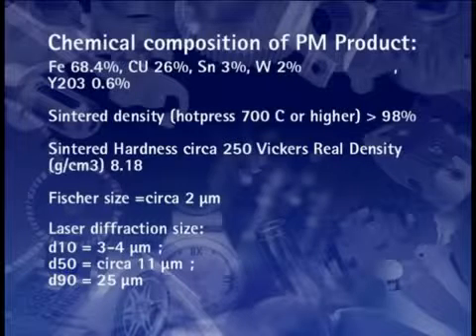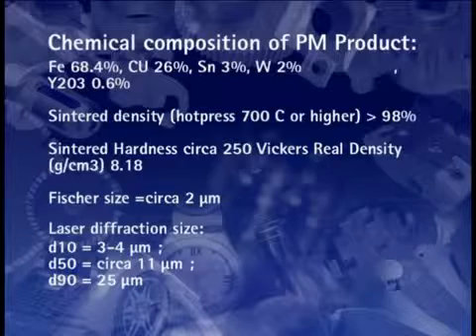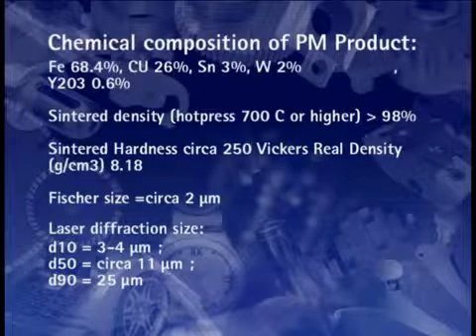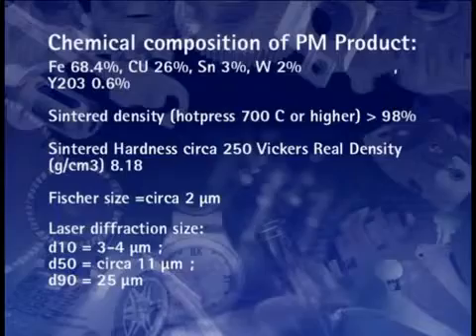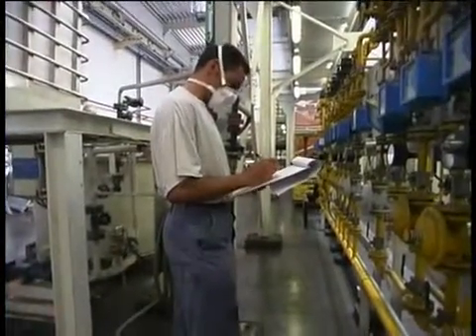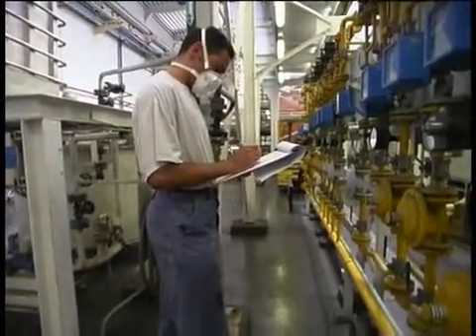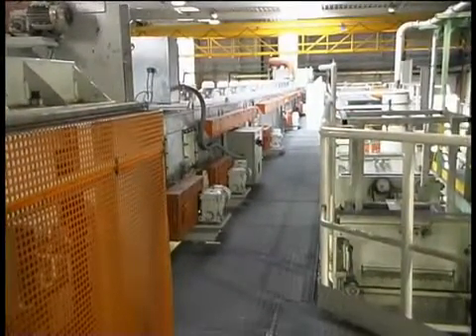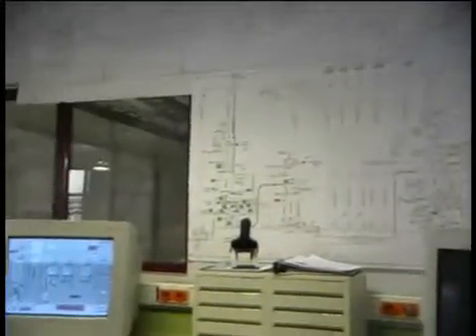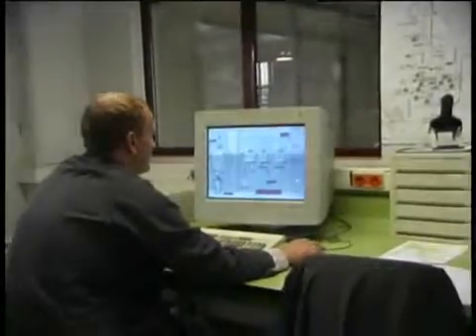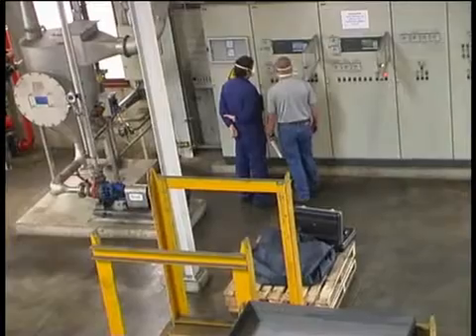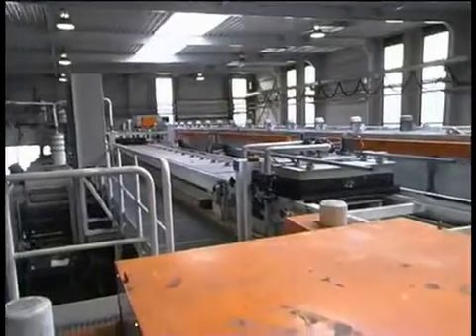Using a wet chemical process followed by reduction, Umicore have produced a cobalt and nickel-free alloyed powder with primary particle size of a few microns that approaches the properties of cobalt powders. This unique powder, which has patents pending, offers a number of advantages to the diamond tool producer. Cost savings of 25 to 50% compared to cobalt powder. A product that consists entirely of elements which are less dangerous to human health than cobalt. Lower sintering temperatures are possible than with alternative materials.